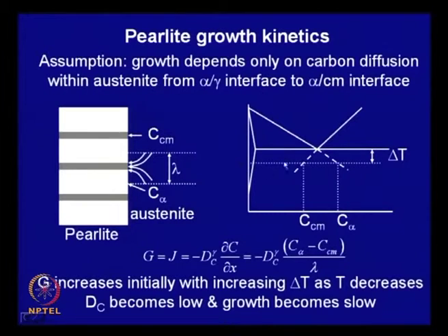So what happens to the surrounding austenite when the cementite forms? This is the carbon concentration in austenite which remains in equilibrium with cementite. So, if you have an austenite grain over here, this austenite will be in equilibrium with cementite, and the carbon concentration in austenite near this cementite interface will be given by this, whereas the carbon concentration in cementite, we know, is 6.67.